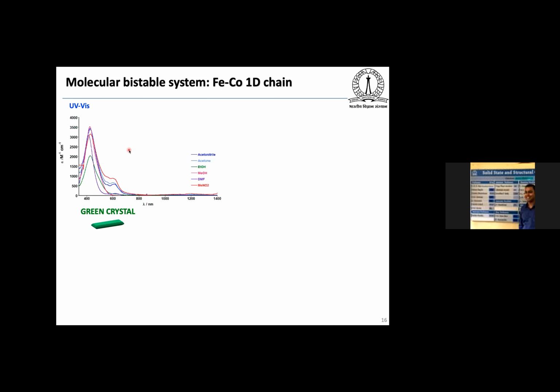And then when you perform the UV spectroscopy in different solvent, then here you can see at around 420 nanometer you have observed ligand to metal charge transfer transition, but at around 600 nanometer you will observe metal to metal electron transfer between the iron 2 to cobalt 3 center. And you can see this metal to metal charge transfer transition you can tune by tuning just the polarity of the solvent.